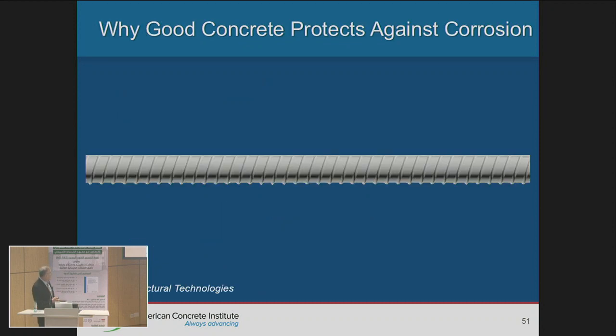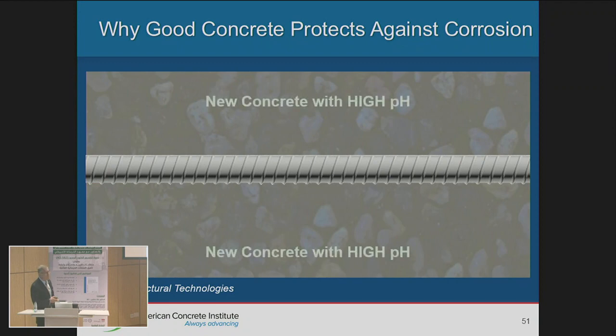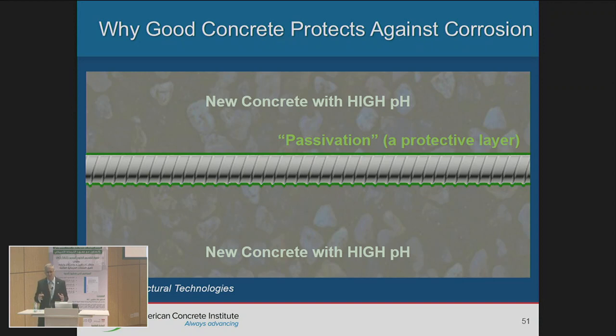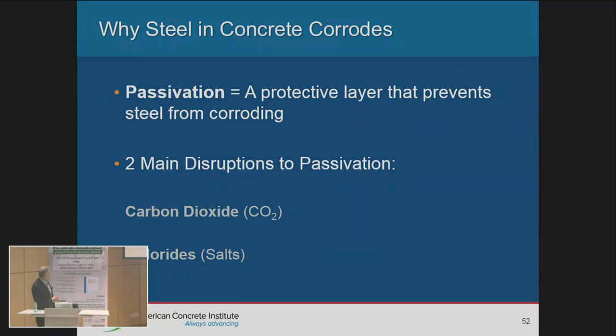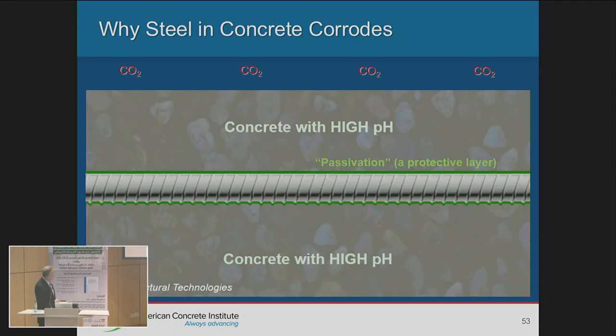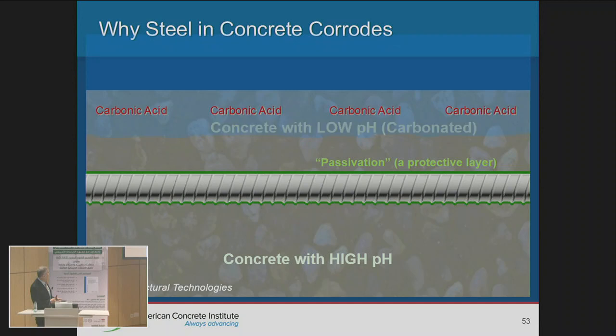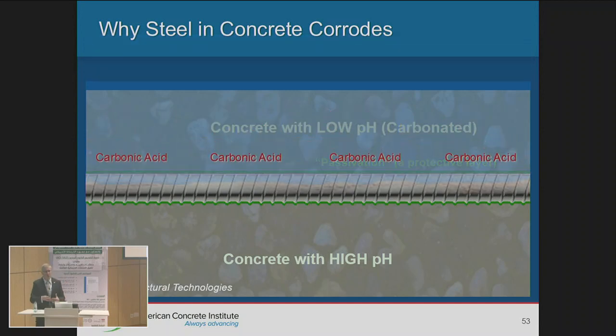Here we have a steel bar, right? When we place concrete, concrete has a high pH number, over 12 or 13. So what does that do? It will create a film around the steel, a passivation that will protect the steel. So over the years, it will protect the steel. But we know that from the environment, we get carbonation, we get chloride. The carbonation may penetrate into the concrete and reduce the pH in the concrete, until it attacks that layer. It will take out that layer, and the steel would corrode.